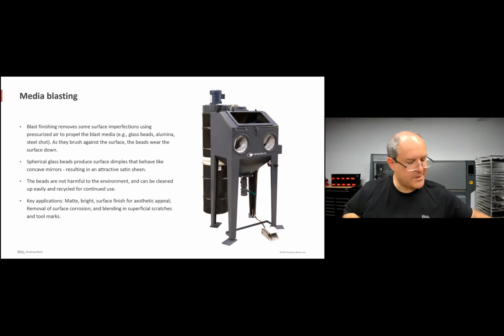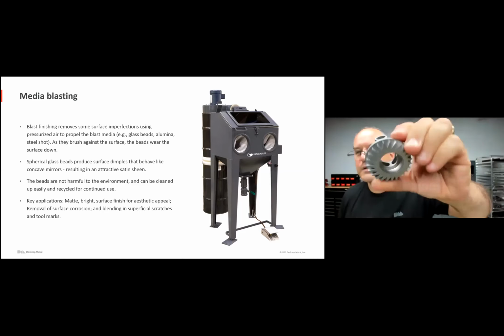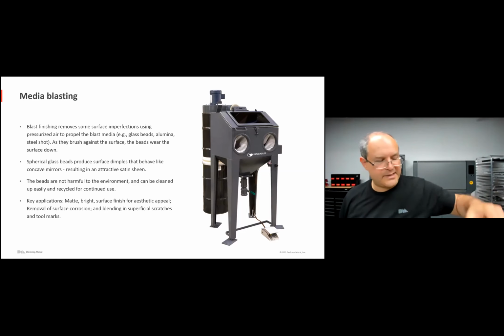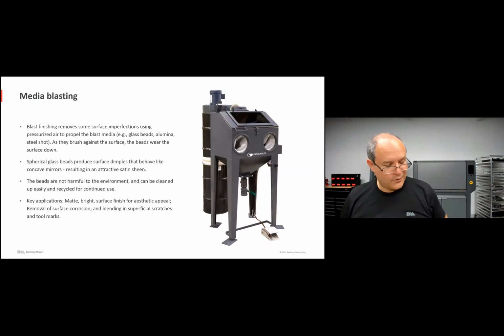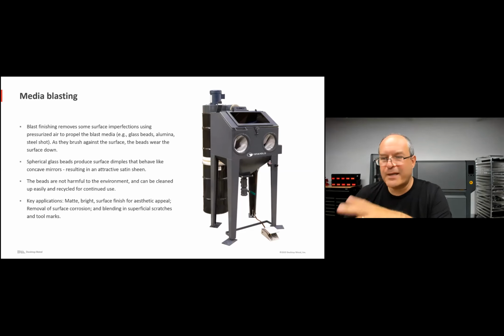So some examples, here's a part that was sandblasted. This is quick enough and easy enough that we really recommend doing this with most metal parts. Now, if you're printing a part that is going to go into the bowels of some equipment, never be seen again, and doesn't come in contact with people for the most part, no problem. But it could be useful to just do a quick media blast. The applications are to go from matte to bright on the surface finish for aesthetic appeal.